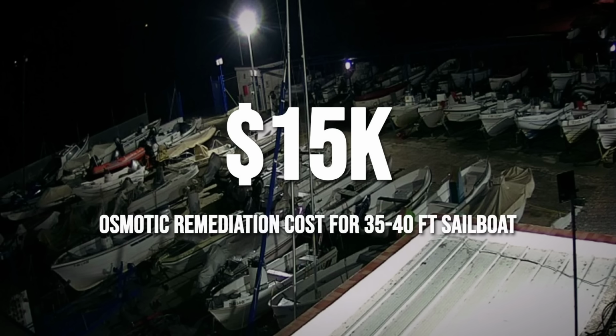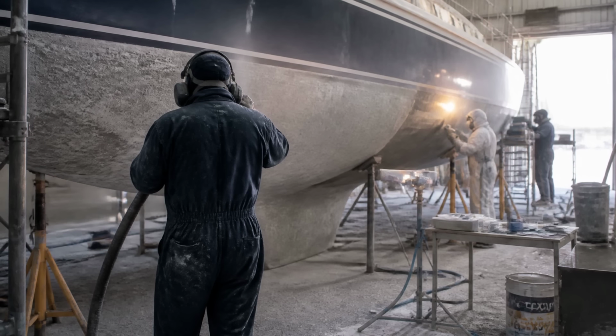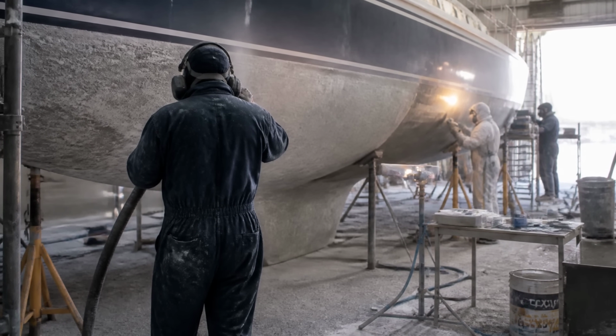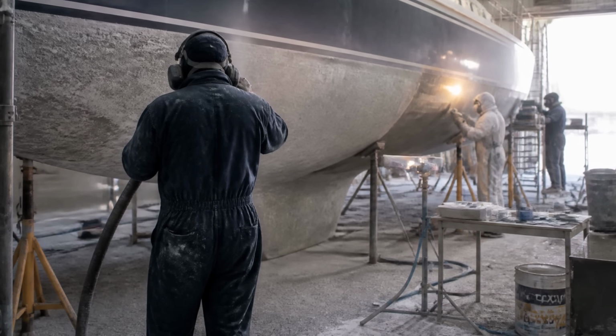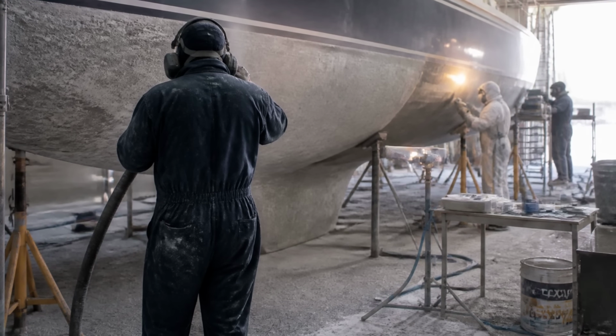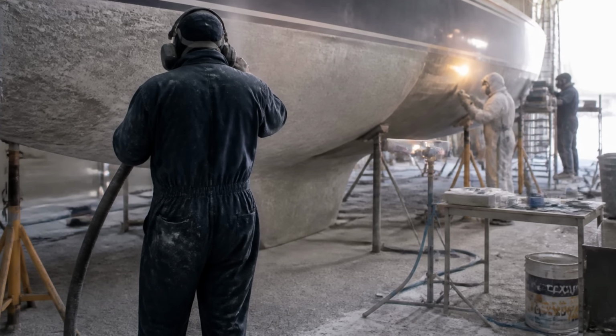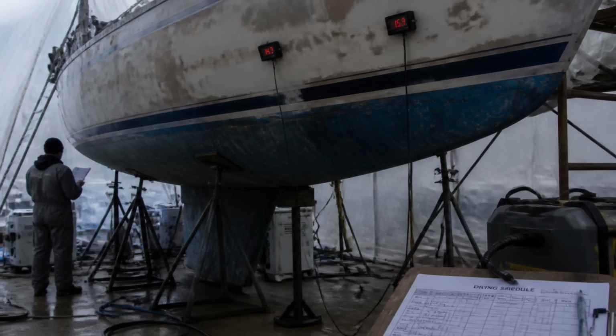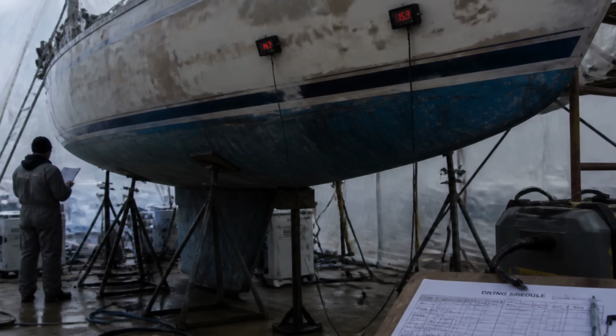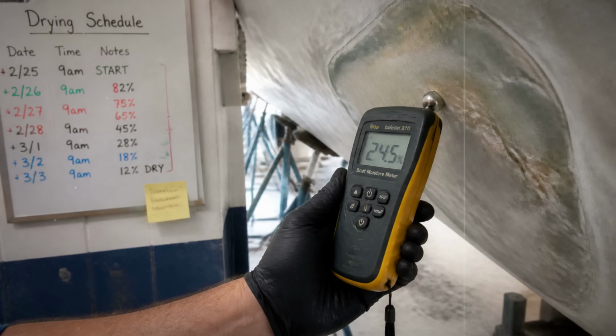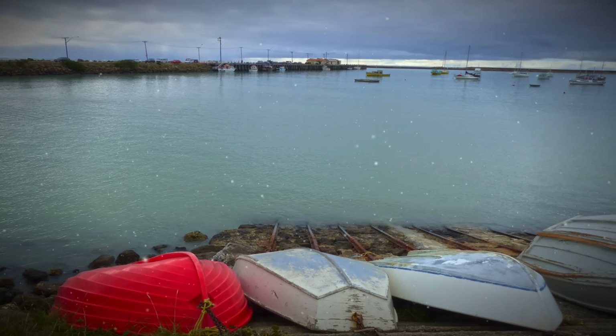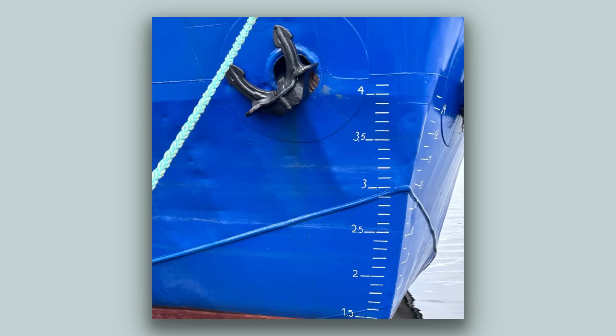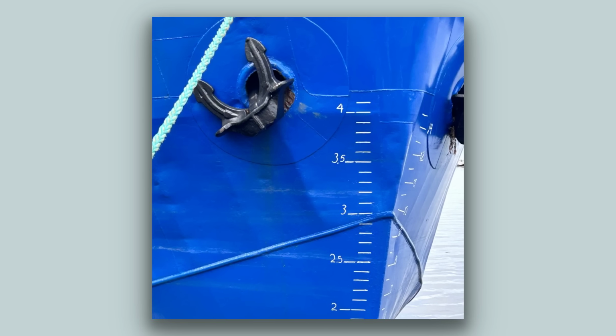Full osmotic remediation on a 35 to 40-foot sailboat runs $15,000 to $30,000. The yard strips the gel coat, blasts the surface, dries the hull for weeks, rebuilds it with epoxy, applies barrier coat, and repaints. The yard dries the hull for weeks, sometimes months. Moisture meters dictate the schedule. You pay storage the entire time. That bill does not exist on a steel hull.